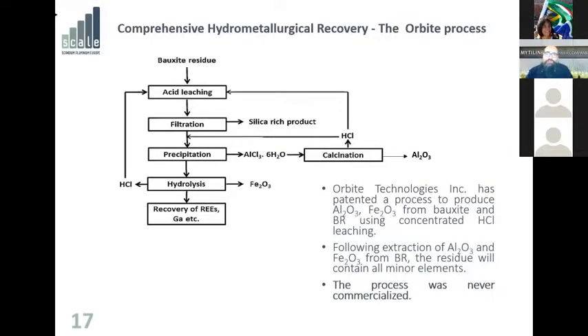So I will try to give a short review of various processes that have been proposed for extracting scandium and rare earths from the bauxite residue. One patented process which came very close to becoming industrialized was the Orbite process, which recovers alumina and iron oxides from bauxites and bauxite residues using concentrated hydrochloric acid leaching. If you follow this extraction, with strong hydrochloric leaching at about azeotropic conditions, you're able to filter out the silica and the titanium phases, which are not dissolving. Then you have a solution that has dissolved 100% of the alumina and the iron and all the other minor elements.